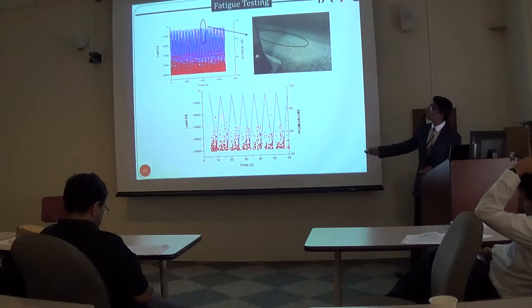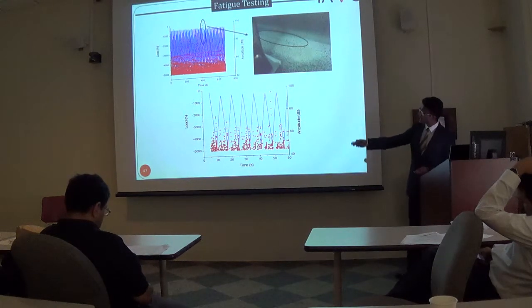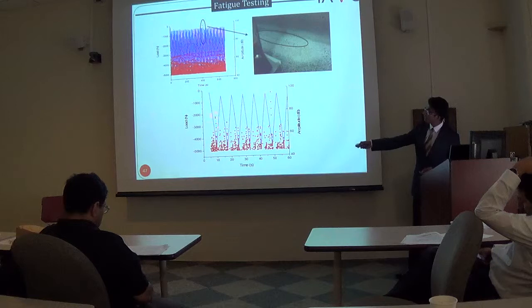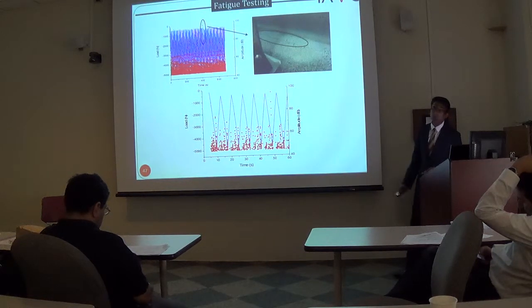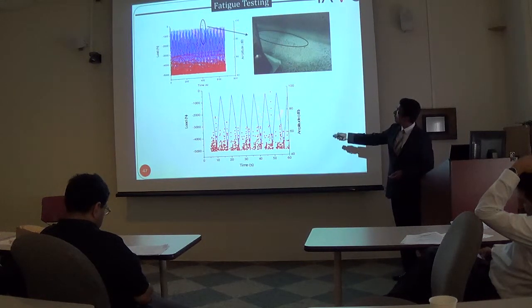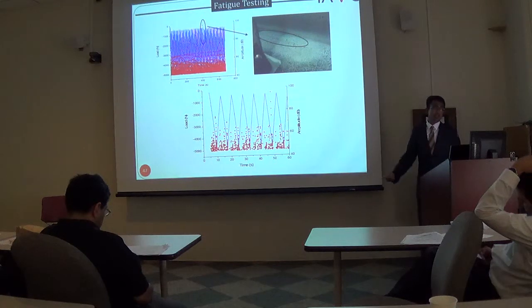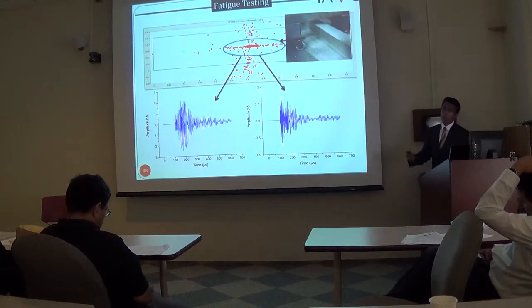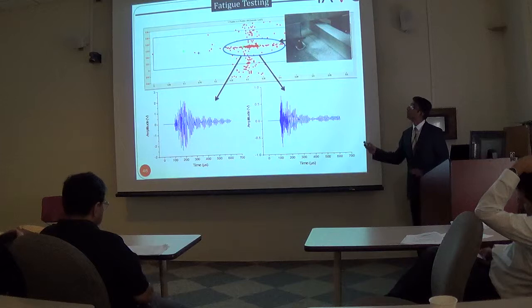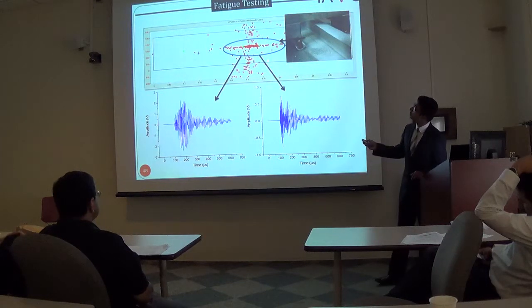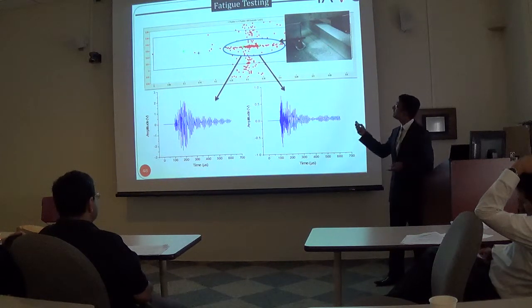These are the correlated AE amplitude with the initial load cycles that can be seen here. And you can see exactly at the peak load, the release of high amplitude signals. And right when we saw the debonding, you could start to see high amplitude AE signals. Now, in addition to detecting them in real time, location algorithms were also employed to detect exactly the